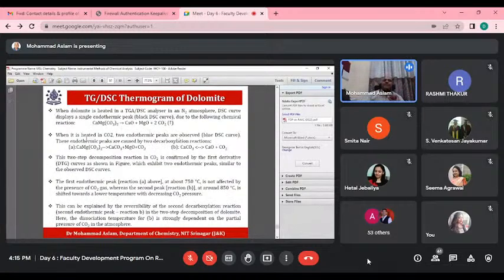When it is heated in the CO2 environment, two endothermic peaks are observed. Why are two endothermic peaks observed? Mostly because here the environment is CO2. The double carbonate of calcium and magnesium decomposes in two different decarboxylation reactions at two different temperatures. The first decarboxylation reaction happens at 750 degrees centigrade, and the other at about 850 degrees centigrade. The first reaction is not reversible in nature, but the second decarboxylation reaction is reversible in nature.